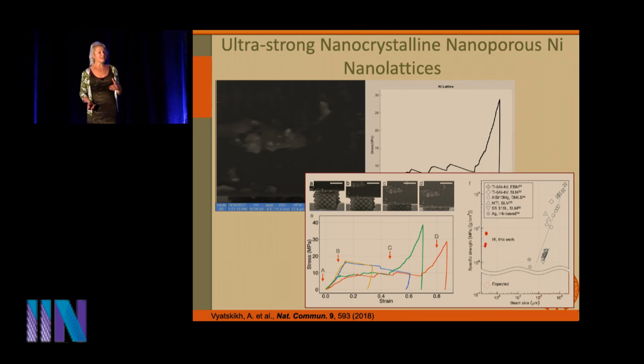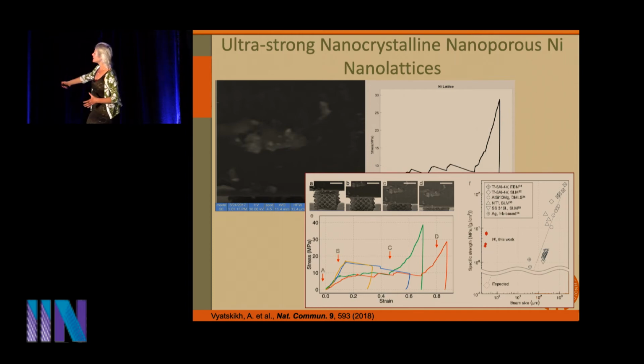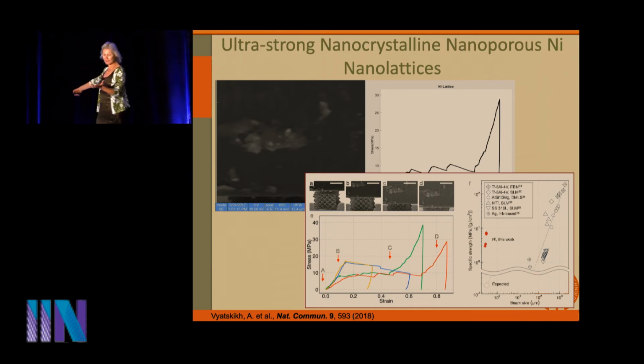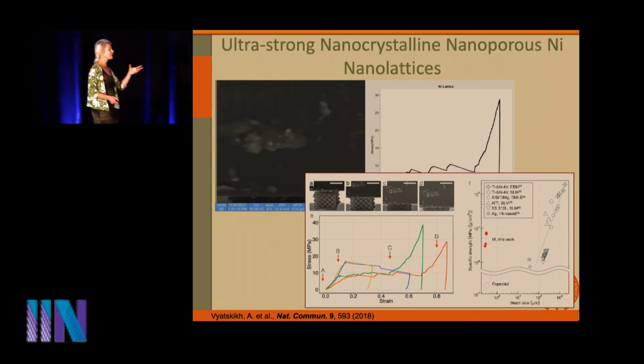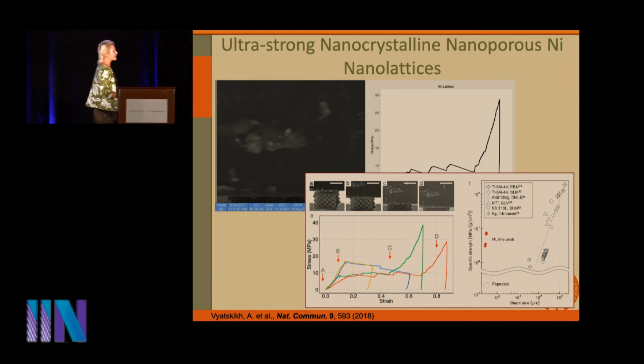So what this tells us is that at the nanoscale, not only do you gain strength benefits, but your materials become much more forgiving to defects. And so the combination of this leniency against the defects, as well as the size effect, propels the strength of these nano-architected nickel materials and other metals to be quite respectable and very much comparable to something that is currently possible only at roughly 1 millimeter or half of that dimension.